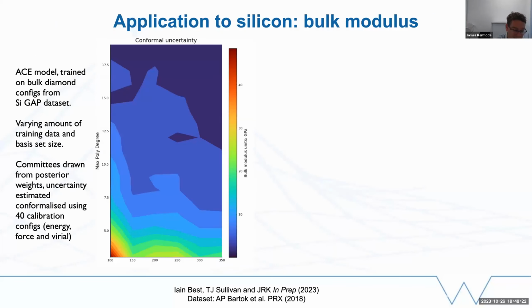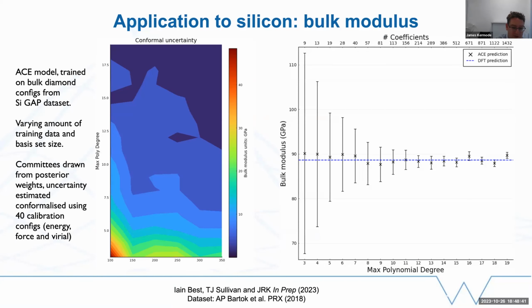And this actually is working pretty nicely. These are some results Ian has got using this same silicon data set that I've shown a couple of times. What we do here is we draw a series of different models, we conformalize them using this approach, and then we use them to get our estimates on quantities, in this case, the bulk modulus.